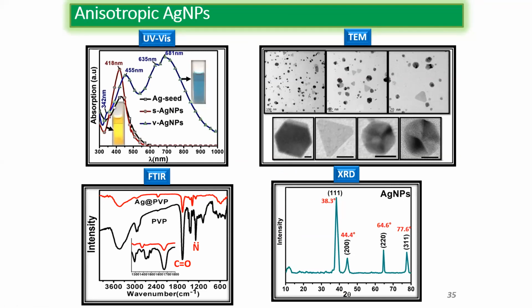I can make all the sizes and all the different shapes of the material. This is the method which I showed previously. This is the TEM image, where we see some triangles, some cubes, some octagons, and some random shapes. Because of this, SPR, as I told, is very much dependent on shape and size, so the UV-visible absorption of this material increases in a broad region.